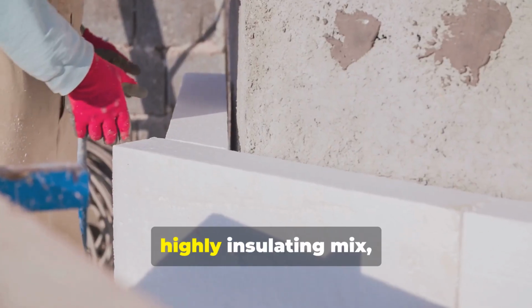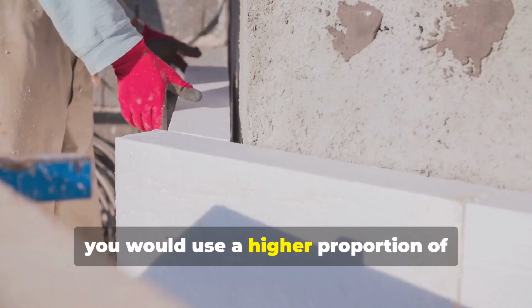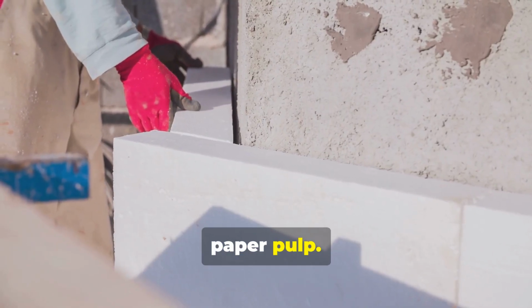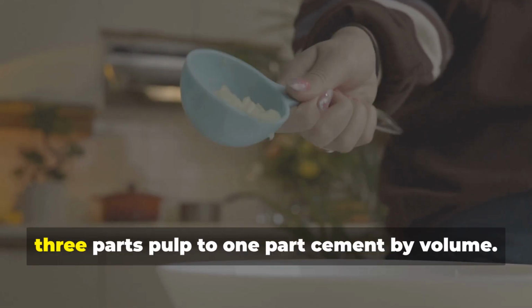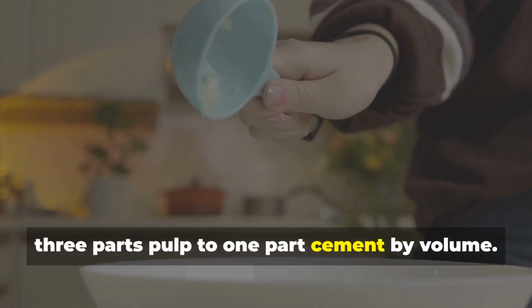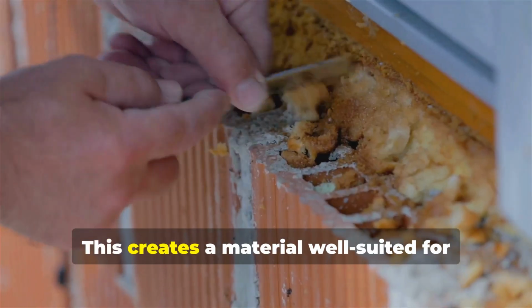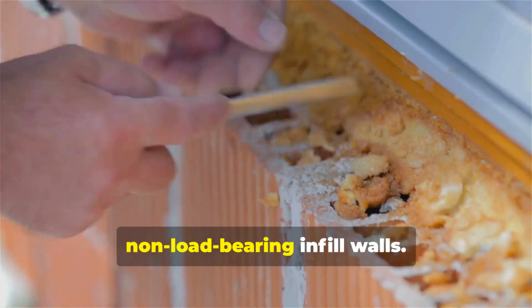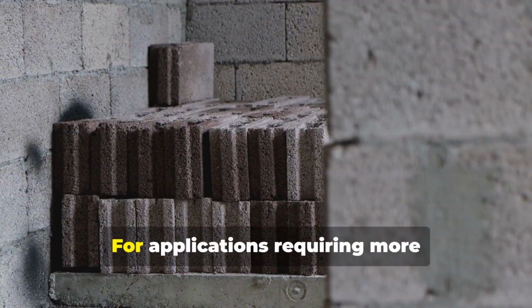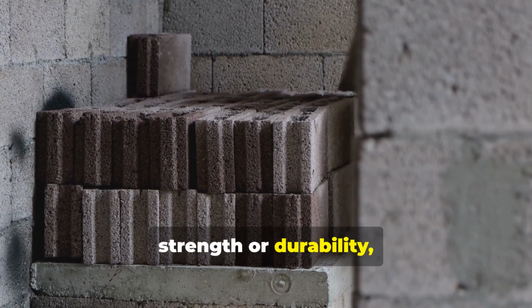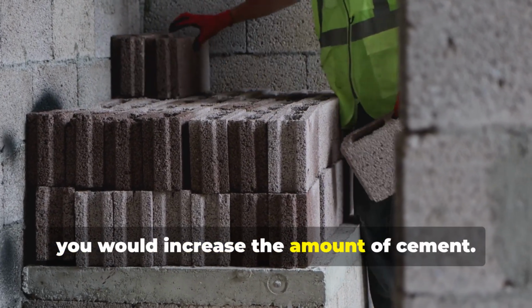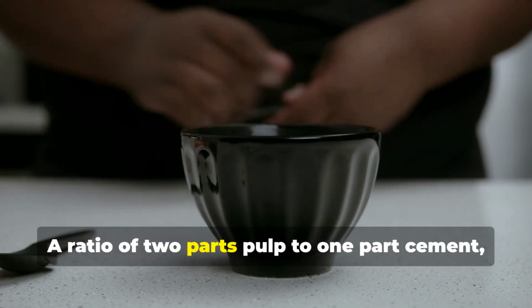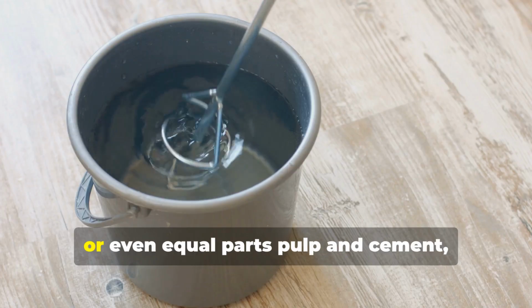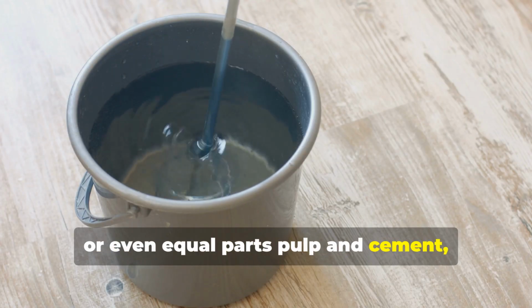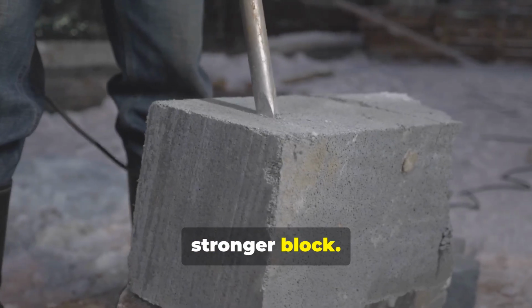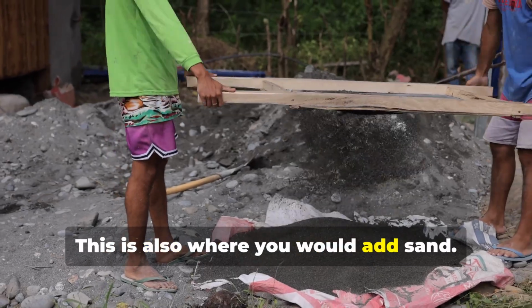For a lightweight, highly insulating mix, you would use a higher proportion of paper pulp. A common starting point is a ratio of 3 parts pulp to 1 part cement by volume. This creates a material well-suited for non-load-bearing infill walls. For applications requiring more strength or durability, you would increase the amount of cement. A ratio of 2 parts pulp to 1 part cement, or even equal parts pulp and cement, will result in a denser, stronger block. This is also where you would add sand.